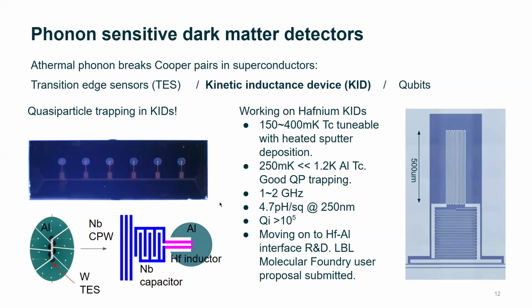So one natural solution is to do similar things for KID, right? We also have this aluminum phonon absorber and use quasi-particle trapping. This is a prototype device I made, but it's not working, and we're trying to understand why. To do so, we need a superconductor that has a lower Tc than the aluminum. There's a specific reason why the collector has to be aluminum, mainly because the quasi-particle lifetime in aluminum is about 3 orders of magnitude higher than in the other common superconductors. So we are looking for a resonator material with much lower Tc than aluminum, and hafnium is our choice.